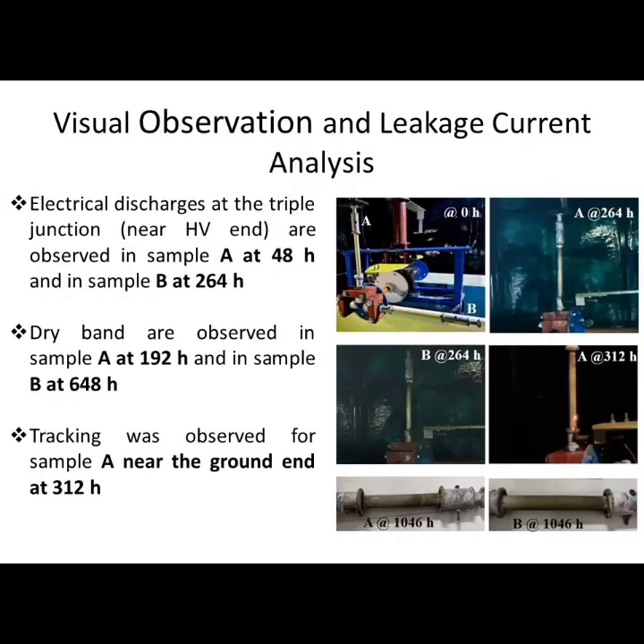This figure shows both samples during the experiment and also at the end of the experiment, where we see here clearly that tracking started in sample A, the normal FRP rod, at about 300 hour. Also, the electrical discharge at the triple junction, due to the electric field enhancement at this point, appears much earlier for the normal sample at 48 hour compared to the tracking resistant sample at 264 hour. In addition, the dry bands along the surface of the FRP rod appear also in sample A much earlier compared to the newly tracking resistant FRP rod. No tracking was observed in sample B during the experiment.